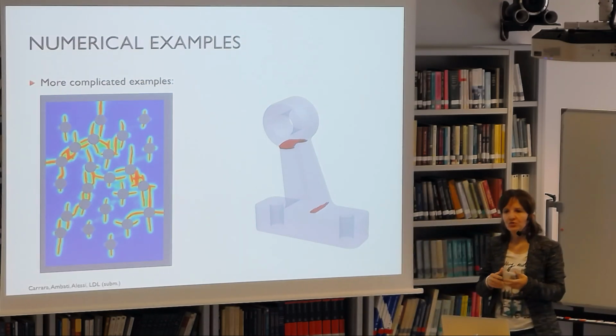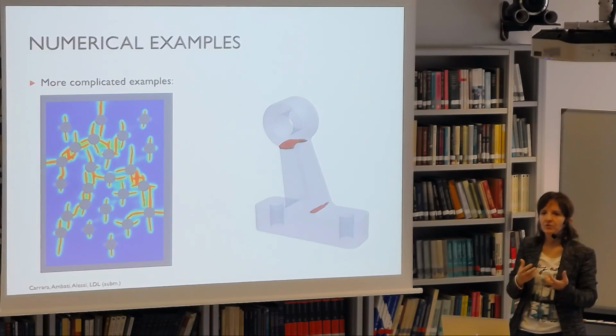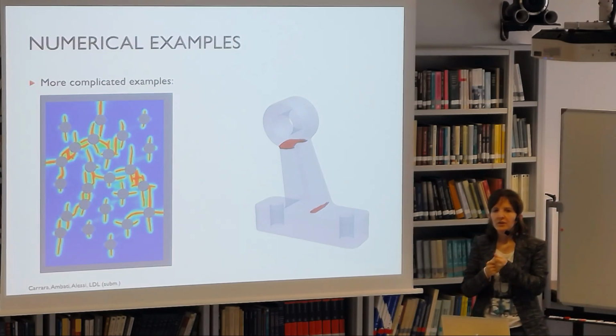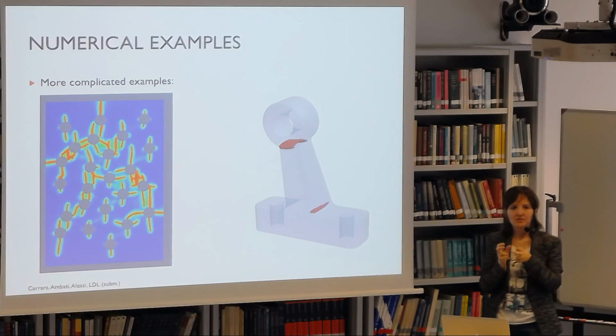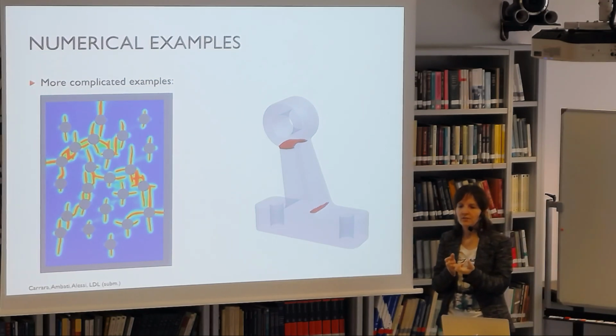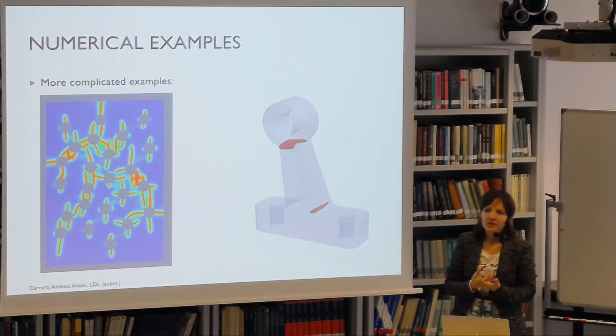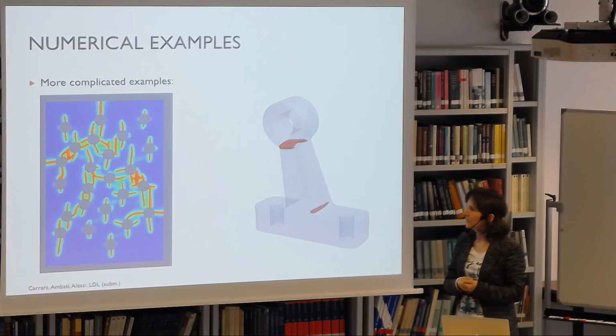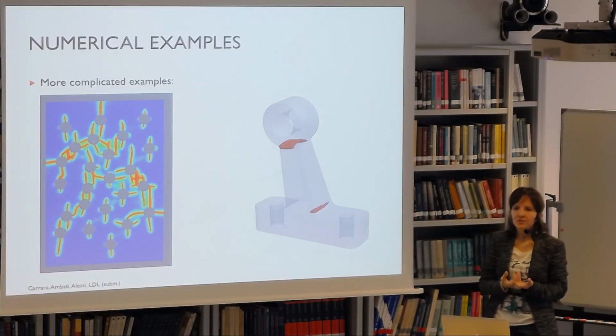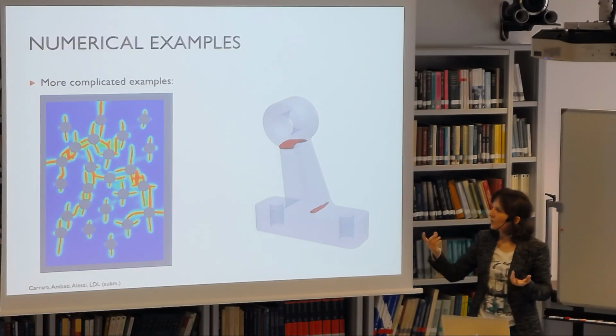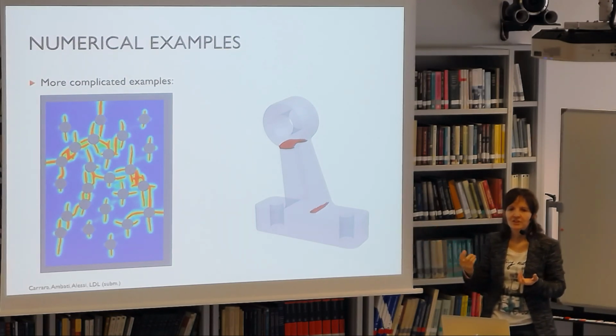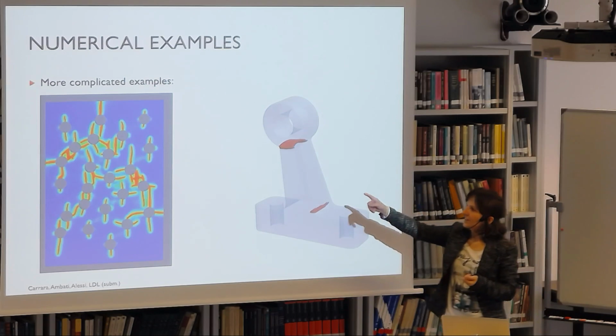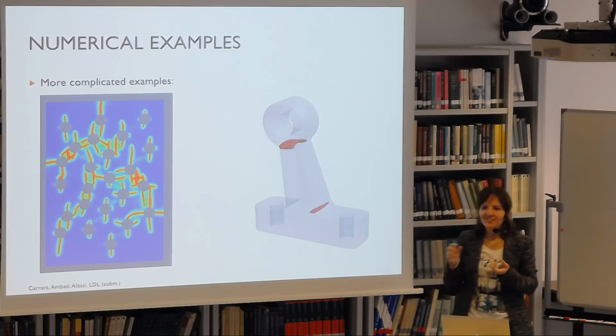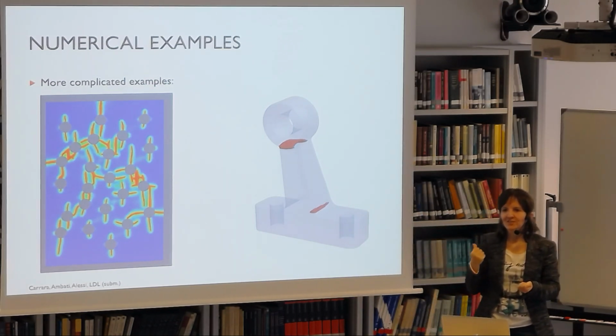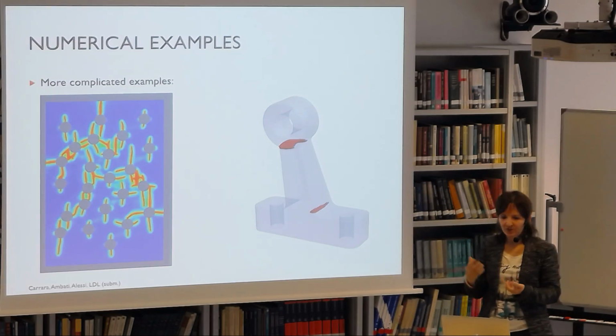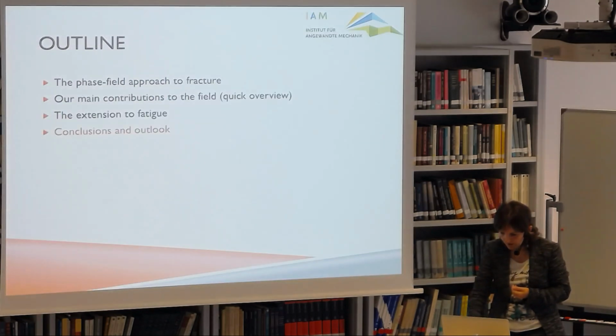So for all the approaches in which you have several cracks, all the standard computational methods based on Paris law or based in general on linear elastic fracture mechanics are very difficult to apply, because you should compute the stress intensity factor at any tip, and any tip of any crack is influenced by all the other cracks. So this would be unfeasible, and instead with this approach you can easily do this.